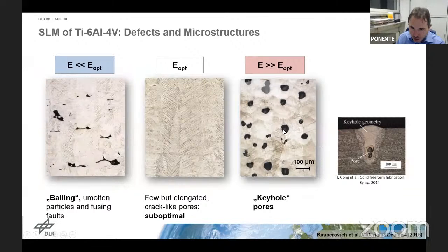This kind with the round pores, well, they are still rather big pores, but even cast materials do possess a certain amount of pores, so that's not untypical for other materials either. And they are at least not as critical in terms of shape. So I'd rather go for a process parameter set that has a few of those pores, rather than risking a parameter set that may have only a single or a few of those kind of pores.